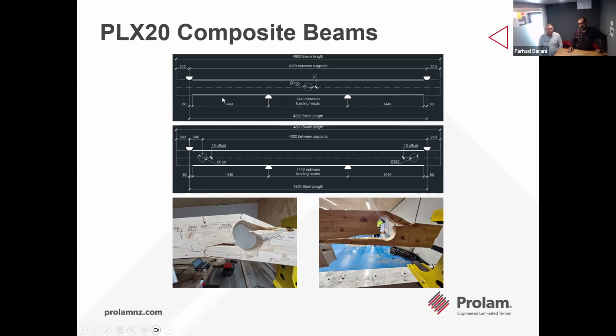The stiffness and strength of the beam was not much affected as we expected, because the failure will be governed by flexure. And then we have done another test with holes very close to the support, to the end supports, and we did the testing. So the failure was governed by shear. So we have a very good understanding of the shear resistance of the beam. And at the moment we are working on a guideline on which diameter and which location the holes could be relative to the end supports. And if we need to get too close to the supports, we can add some additional steel plates for reinforcement.